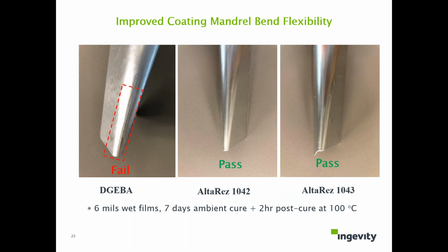And for the mandrel test, our diol epoxy 1042, 1043 all pass the mandrel test, so they are very flexible materials. And the control sample, you can see they have some cracking after this mandrel test, so it failed.